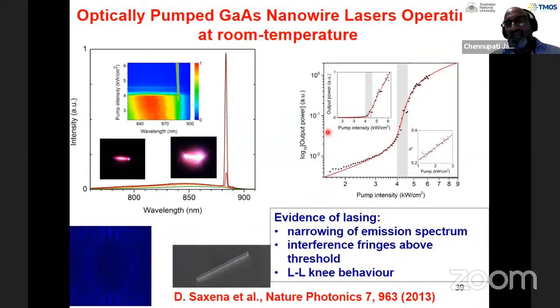You can also see the output versus pump intensity. You can see the nice threshold-like behavior here. And a log-log plot of this output power versus pump intensity shows this S-type behavior, which confirms that true lasing is taking place in the structures. You can also see beautiful interference fringes coming from when these nanowires are lasing. And D. Saxena, in fact, has done simulations to compare the interference fringes you expect from a 6 micron long nanowire with respect to the measured ones, and he is able to compare these theoretical simulations with experimental results very well. And these are the first gallium arsenide nanowire lasers operating at room temperature, published about 7 years back or so.